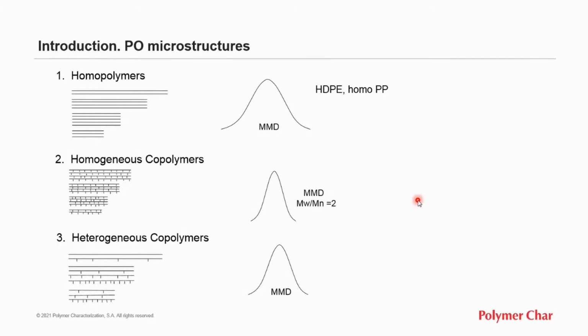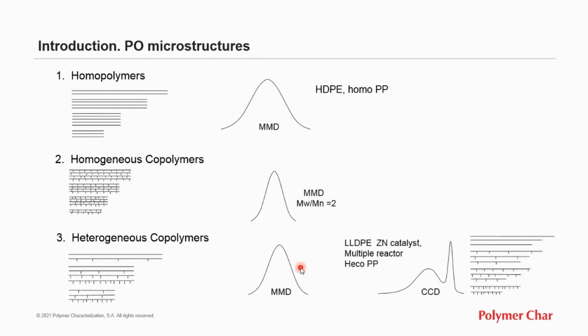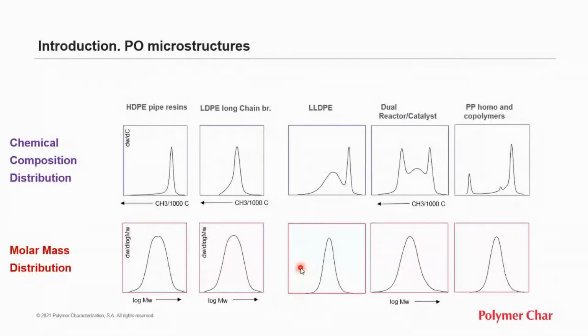Very important to keep in mind then is that polyolefins are polydispersed products, meaning they exhibit a distribution in molar mass, which can be broad or narrow, which in some cases is enough to characterize them, as in the case of homopolymers or homogeneous copolymers. But in the case of heterogeneous copolymers, there is also a distribution of chemical composition, which may be very complex, as in the case of Ziegler-Natta LLDPE, we see in this figure, or heterophasic impact polypropylene and some others.